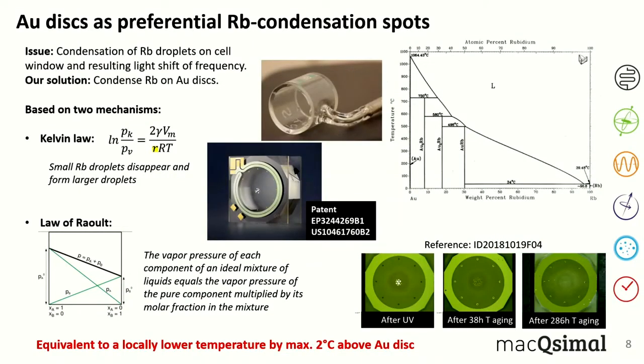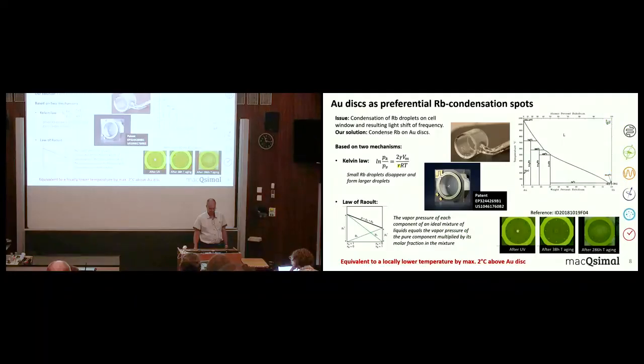So this technique is equivalent to having a locally lower temperature by a maximum of 2 degrees above the gold discs. And this is sufficient. This does not have to be heated or powered or anything else. This is constantly the case. It's always lower above the gold disc, so all the rubidium will go onto this gold disc, and there is no or only little rubidium that remains on the cell window and will thus impact the clock frequency.